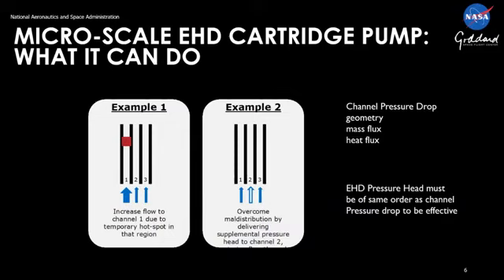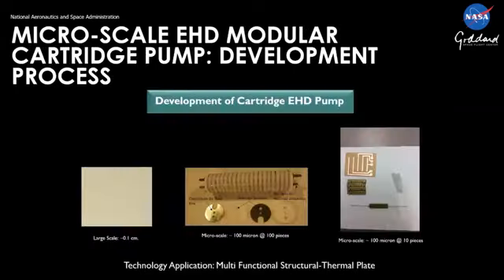So what can the pump do? Basically, in the configuration which we developed, you have, again, an arbitrary number of manifolds, in our case 5, but in the case here we have 3. You can increase the flow in any given channel to pick up heat or handle a temporary hotspot, or as we show on the right in example 2, you can overcome flow maldistribution. That's just reality. No matter how well you design any manifold, the pressure drop across the manifold is not going to be uniform, and one channel will get starved relative to another channel. However, with an EHD system, you just up the voltage and you can correct for that. So if we move on to the next chart, please. And this is all for single phase flow.